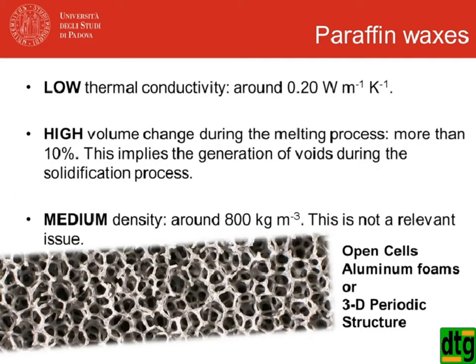How can we solve the problem? The low thermal conductivity, 0.2 watt per meter Kelvin, implies the need of the use of extended surfaces to allow the heat to be stored and then rejected from the thermal energy storage, or used. We can say stored and then used.